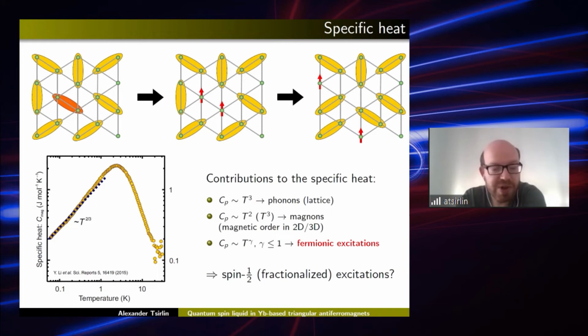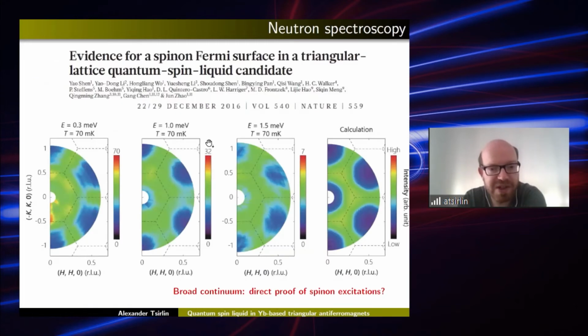Then, of course, you want a more direct probe than just looking at the specific heat. So you go to neutron scattering, and then you realize that someone else already did it. That was the case for this compound, where the Chinese group led by Jun Zhao published this Nature article in 2016. And they measured the magnetic excitations at very low temperatures and very low energies. If this material were anything conventional like an antiferromagnet, then they would just see the spin waves, so they would see just some points in these energy cuts. But instead, they saw a broad distribution of the scattering intensity, which is again typical for these fractionalized excitations.